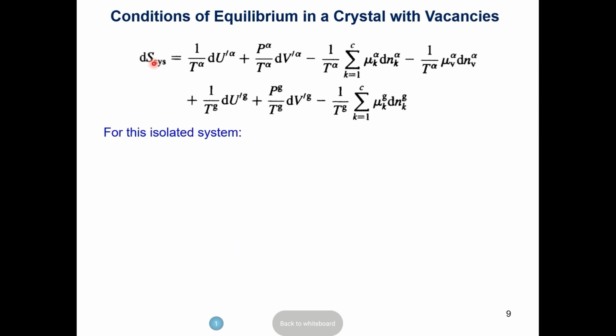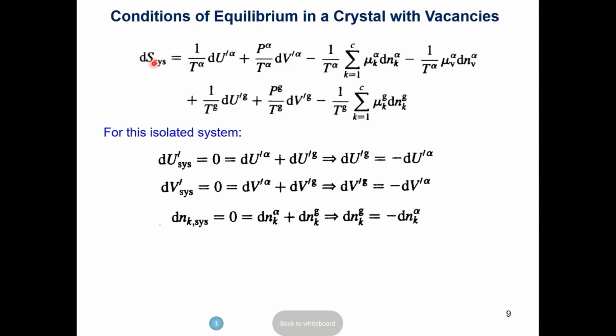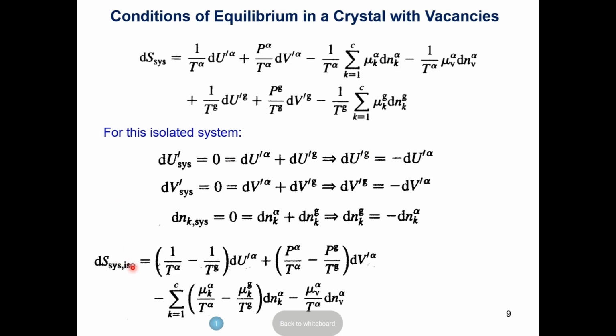If you recall your second law of thermodynamics, for a system where you're looking at sample plus surroundings, which is an isolated system, all the changes have to be zero—internal energy, volume, number of moles, etc. As a consequence, you'll see the changes have to be equal and opposite. That makes sense intuitively because that's the exchange: whatever is coming out of the solid is going into the gas phase, or whatever is being incorporated into the solid is coming from the gas phase. So you can use those and rewrite your change in entropy of this isolated system, sample plus surroundings.